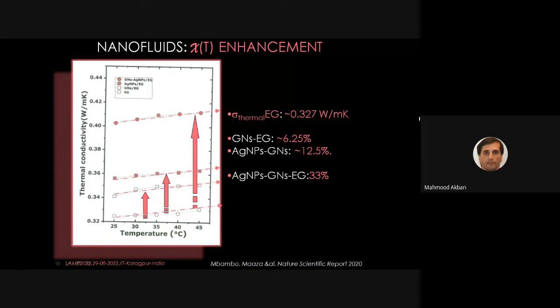Here, colleagues, is the thermoconductivity for different systems. The first one at the bottom is the thermoconductivity from around 20 degrees Celsius up to 45 or 50 degrees Celsius. This is unfortunately the limitation of the hot wire, because out of this range there is a huge amount of fluctuations. So just to be safe, we represent only the thermoconductivity within this range. The first curve at the bottom, the open circles, is the thermoconductivity of pure ethylene glycol. You can see it's around 0.327 watt per meter per Kelvin.